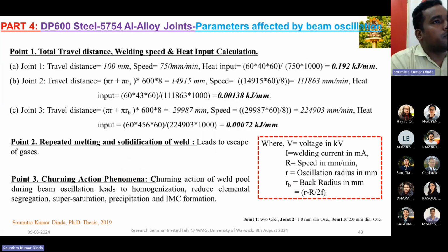And we also calculated what is happening in terms of actual heat input. That is calculated by the back radius and the normal radius when we are rotating our welding beam with beam oscillation condition. And this is the point. What will be the point? Point 2 is the repeated melting and solidification, that will give more than enough time for gas to escape from our material. And the third point may be the churning action phenomena. The churning action of the weld pool during beam oscillation leads to more homogenization, or reduces the elemental segregation, supersaturation, or intermetallics formation.